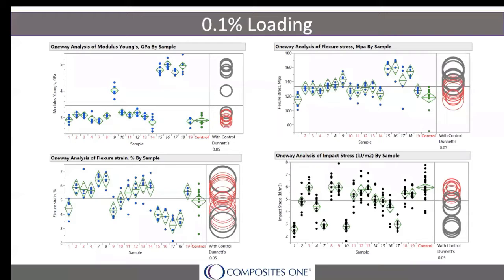So if the circle is shown in red, it simply means that those results are not statistically different from our baseline, and so we consider the difference negligible. But if the circle is in gray, it means that the samples tested had enough of a difference from the baseline that we could be confident that there is a significant change in results, either positive or negative.